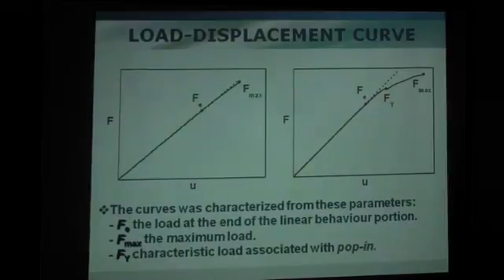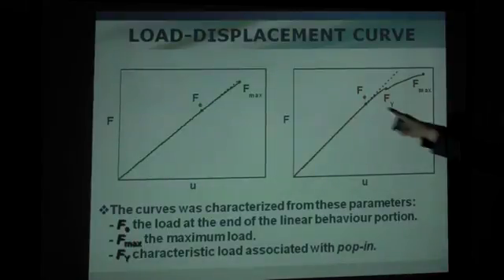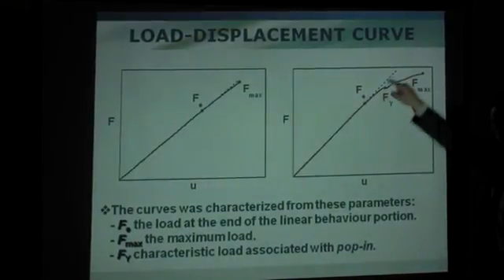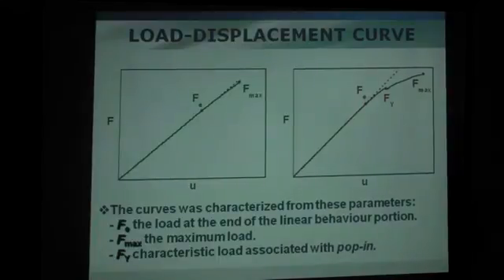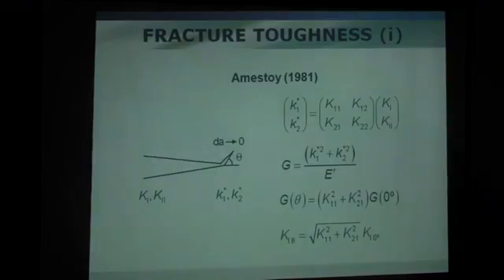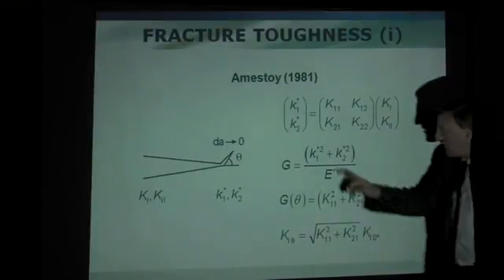Then we define the maximum load, and Fy, the limit of the linear or elastic behavior, which is not plastic yielding but micro-tearing by an anisotropic resource. This is crack splitting or delamination. This is the phenomenon we have observed by stopping the test and performing a fractometallographic analysis, an analysis of fractured pads or crack pads with metallographic polishing. We call it fractomaterialographic or fractometallographic analysis.